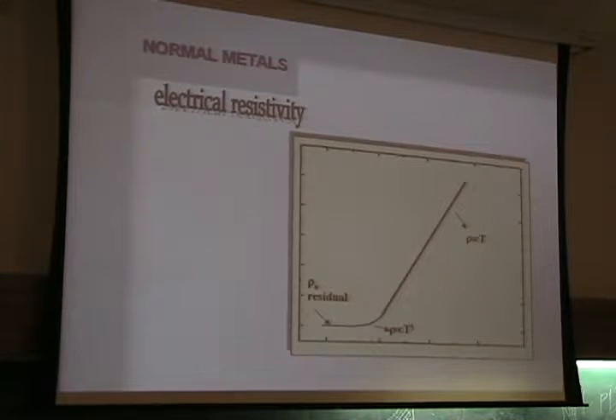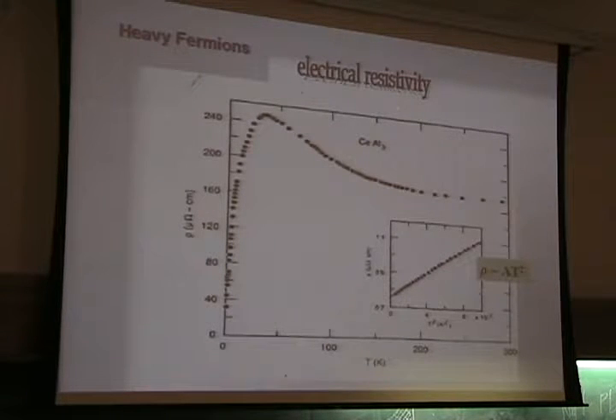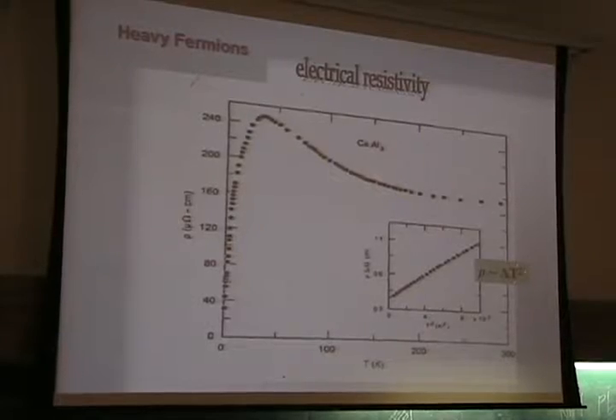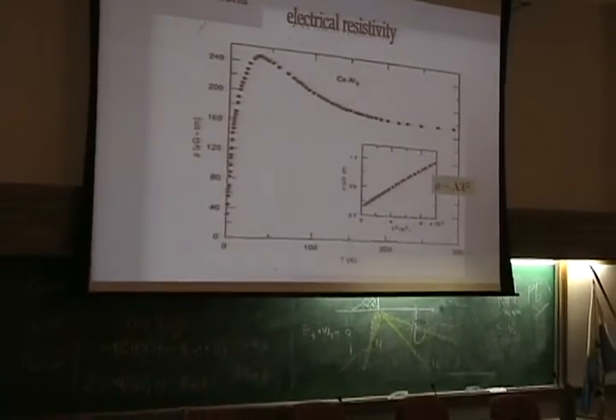Also, the electrical resistivity of a normal metal is dominated by phonons, and at very low temperatures, actually for some metals below 20 K, you have a contribution to the resistivity that is independent of temperature. That's the residual resistivity, which is dominated by defects, imperfections of the lattice, and impurities. But in heavy fermion materials like cerium aluminum, you have a contribution that is proportional to T squared. That is the electron-electron contribution. And you see here at low temperature, this is the inset.